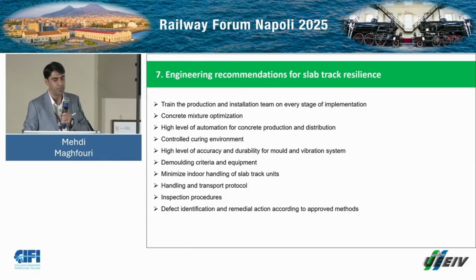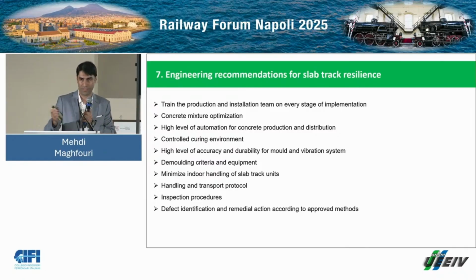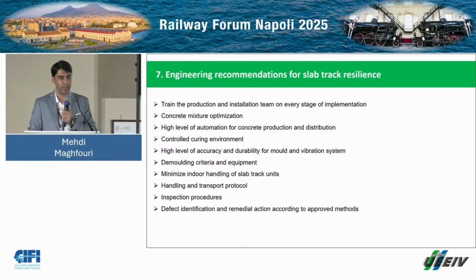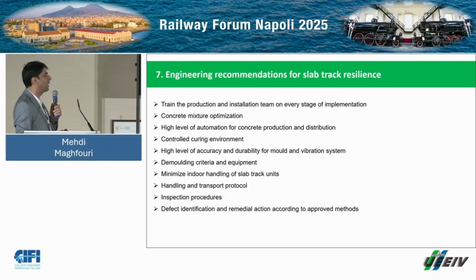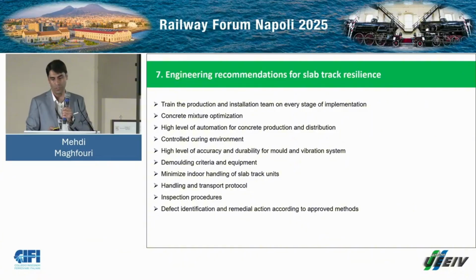Control the curing environment, with a high level of accuracy and durability of the mold. The mold is very important. If you have a complicated mold, the demolding would be very difficult and tough, with so many defects. And then demolding criteria and equipment shall be there, minimize handling of the slab track, and then handling and transport protocols shall be there, and inspect the procedures from time to time. And last but not least, defect identification and remedial action according to the approved method statement.